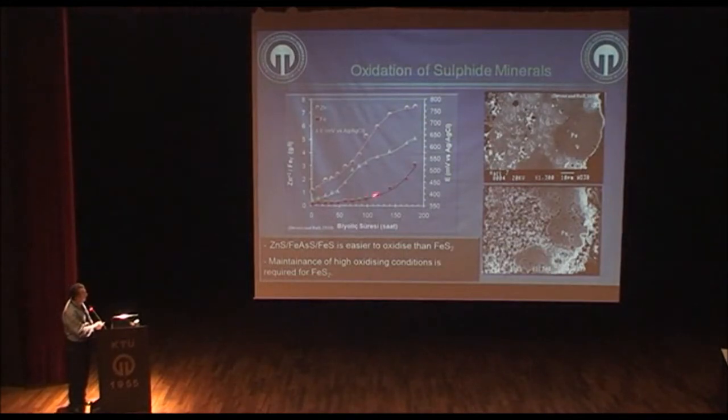And we can see here the oxidation of pyrite. We can take this one as the iron profile. The oxidation of pyrite will only occur after a certain redox potential, which is about 550 millivolts. But sphalerite can be easily oxidized beforehand.